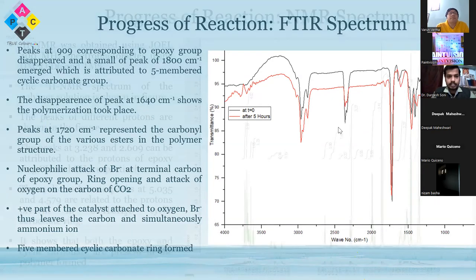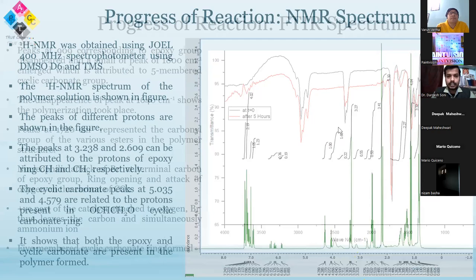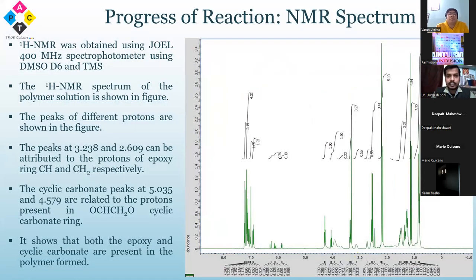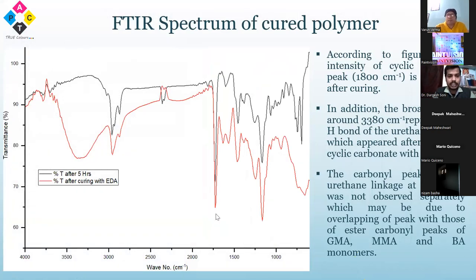Again, it was also confirmed by the NMR spectroscopy. And this is the reaction after curing with the ethylene diamine. Again, the same things were there, like the cyclic carbonate group peak disappeared and the new peaks corresponding to the carbonyl group and hydroxyl group emerged, which confirmed the curing of the reaction.